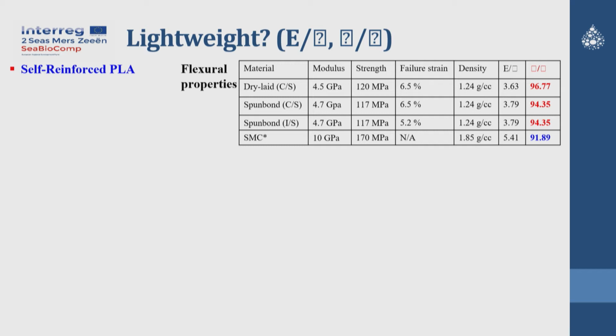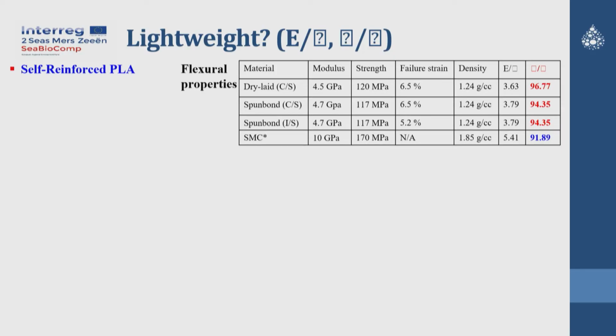If we design a new product, we always consider specific stiffness and specific strength. That means mechanical properties divided by the density. This ratio determines the lightweight performance. If you compare the last two columns, especially the last column, which is the strength divided by the density, you can see that this self-reinforced PLA is equivalent or maybe a little bit better than the SMC in terms of specific strength. So that means we can reduce the structural weight of the final product if we use this material.